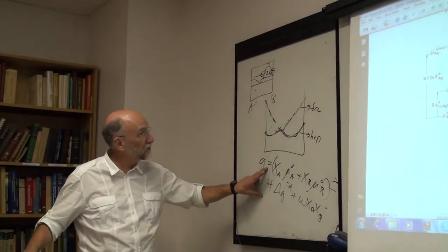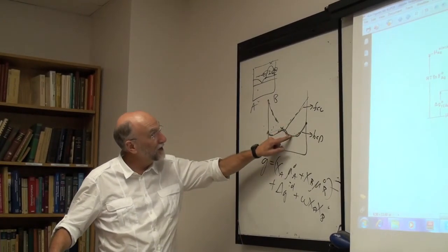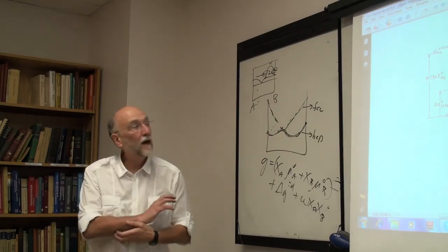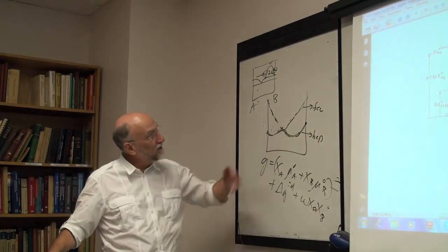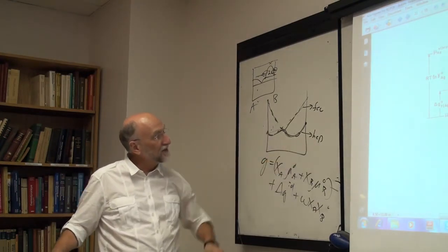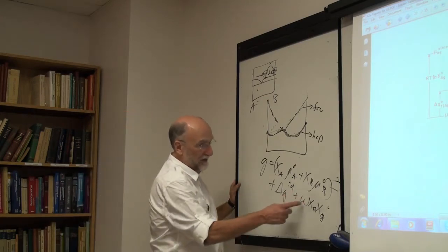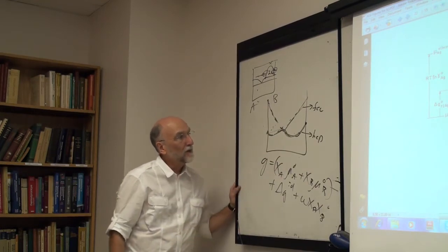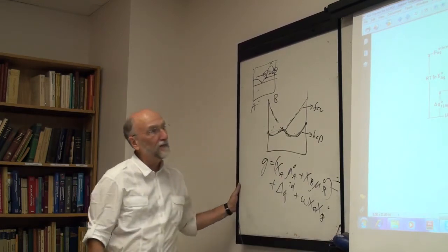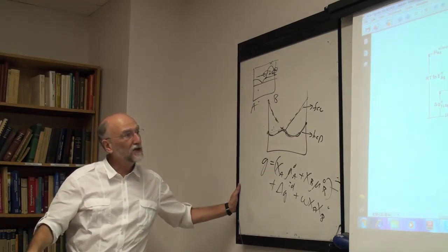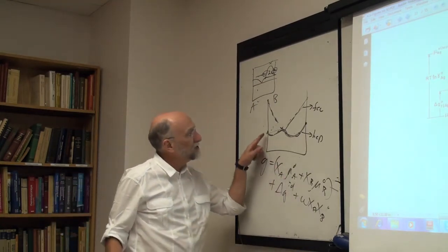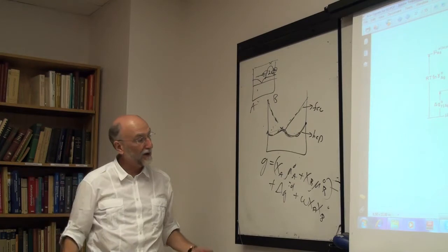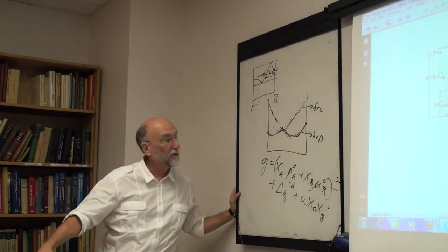So if you're going to do it this way, you're not going to be able to fit it as well in the limiting regions unless you add a lot more terms. But okay, so you add a lot more terms and you fit the thing up. The point is though, you're never getting exactly the same composition dependence. This cannot be related exactly to what you had before in the two, but it's fairly close. Okay, the problem is, what happens is that we find not many, but several solutions. Actually, what you're assuming here then is you're assuming an ideal mix. This is a regular solution, and even if you add the additional terms, you're assuming a regular solution with linear dependence of the parameters on composition.